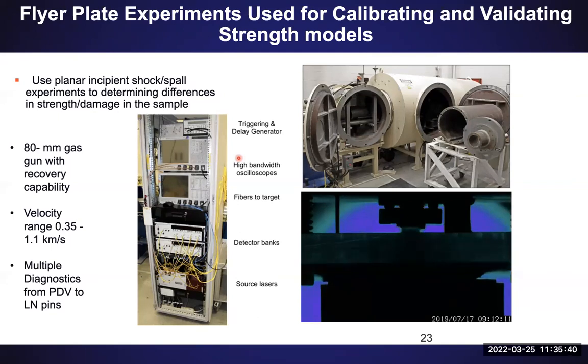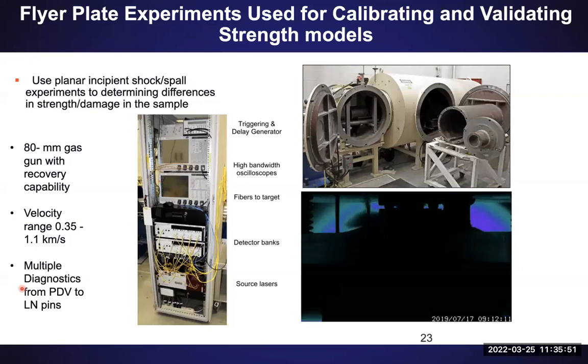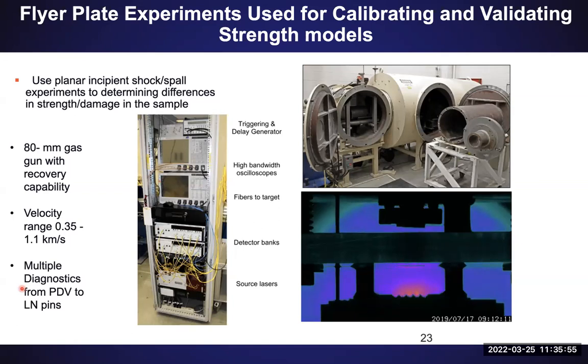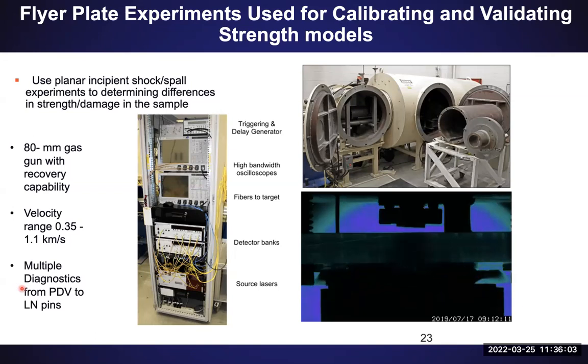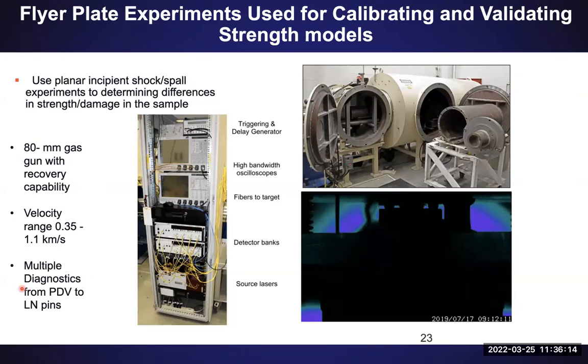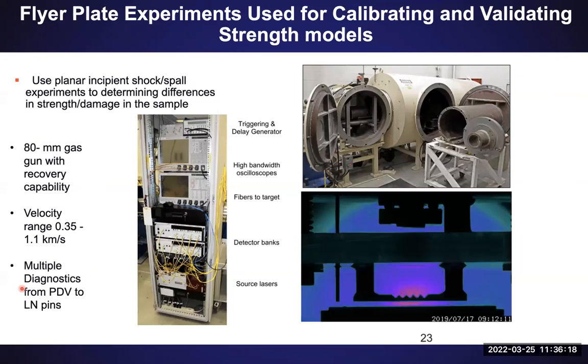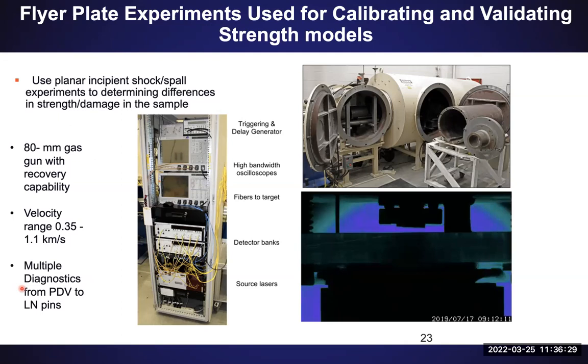Anyway, so we use photon Doppler velocimetry as one of the large in situ diagnostics. And what that really is, you shine a laser of known frequency and wavelength on the backside of your sample. As that sample is moving or being accelerated, there's a shift in frequency, which you can relate to velocity, kind of like when you're in traffic and you hear an ambulance as it gets closer to you, the way the siren sound changes. That's basically the diagnostic we use to figure out the velocity as a function of time as the sample is being shock loaded. We also have capability to do high-speed imaging.